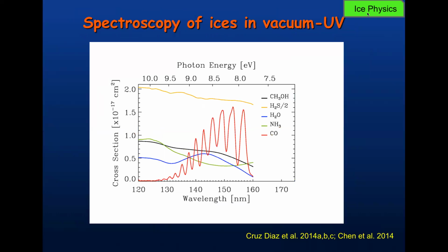We also measure the UV absorption of different ices, which you can see here. This is important because you know how much of the UV is absorbed by the ice and the dependence with wavelength. So we get the absorption cross sections in the UV of the ice, most of which were not measured before.